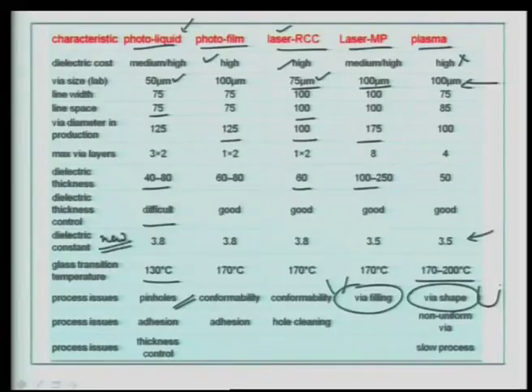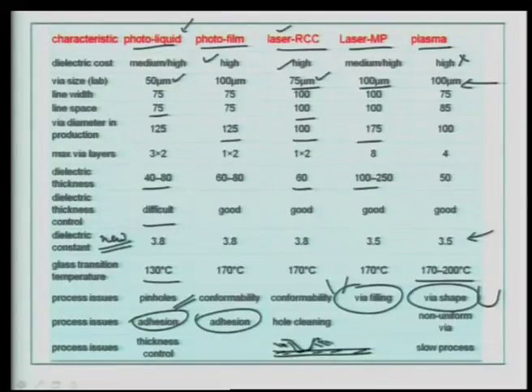The other key process issue that all of us have to be aware of is the adhesion. What is the adhesion we are talking about? We are talking about a dielectric material that is coated and on which a via is formed. So, we are talking about the plating of the via, and there is the dielectric material here. We are talking about the adhesion at the surface of the dielectric to the copper. Now, if there is delamination of copper from the adhesive from the dielectric material, then your microvia has failed.